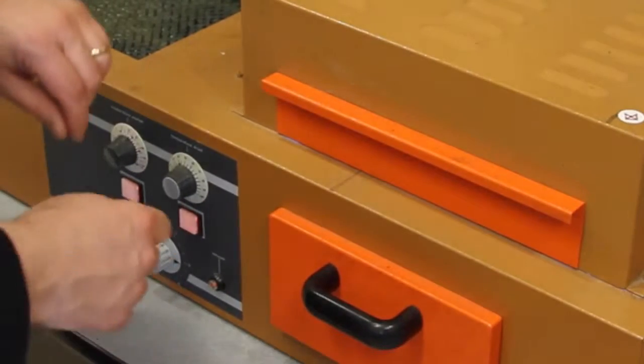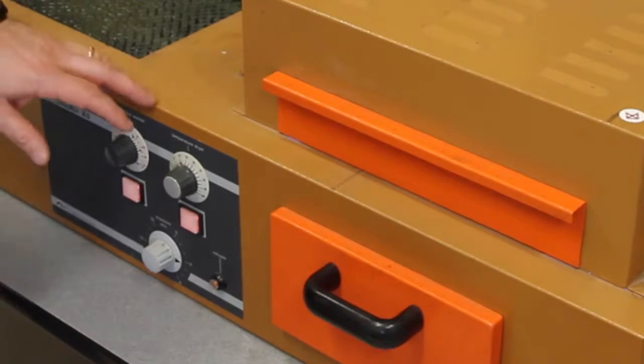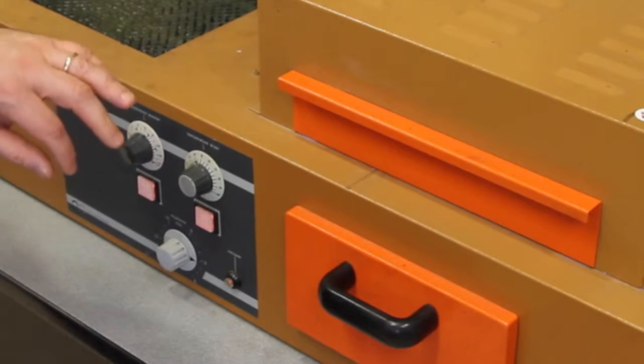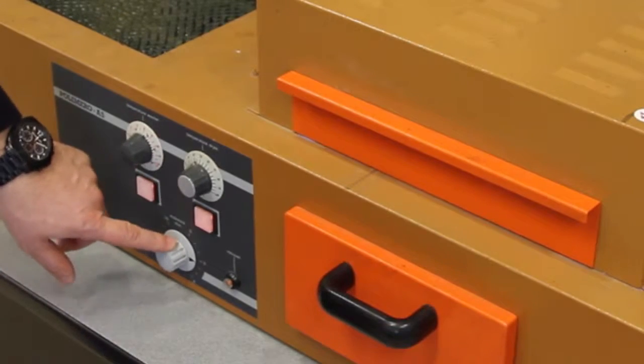Unfortunately this timer doesn't work very well, it's about 40 years old, and so we want to make sure that we have a proper exposure of three and a half minutes for this particular ortho film combination with polymer plate and given the age and exposure of our lamps. All these factors figured into three and a half minute exposure.